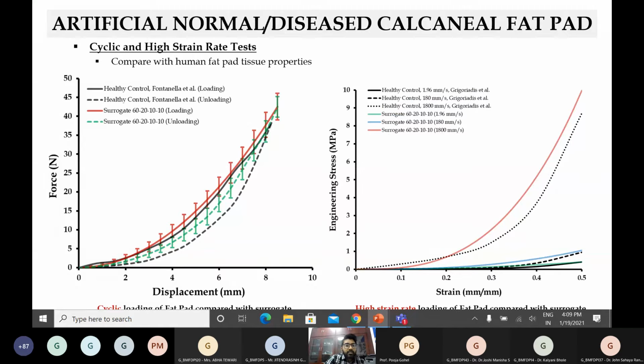All right, so the next thing is cyclic and high strain rate tests. We got a control specimen, called 60, 20, 10, 10. That is basically our composition, and we are calling this a healthy control. We took this surrogate through a massive amount of loading and unloading cycles, and we compared that with our healthy control specimen. What we found is this is very similar in this aspect, with the soft tissue properties which we got from literature or from realistic tests.